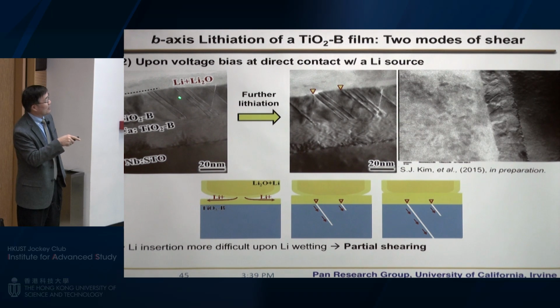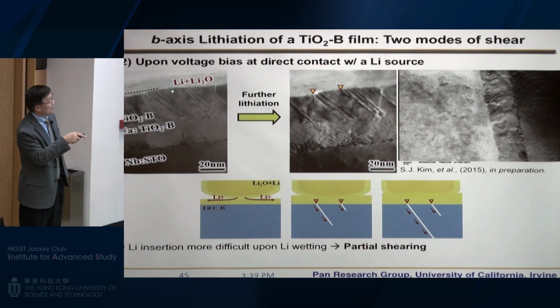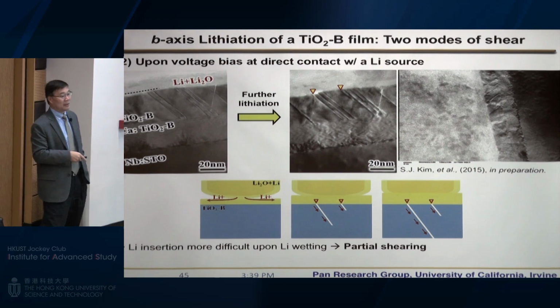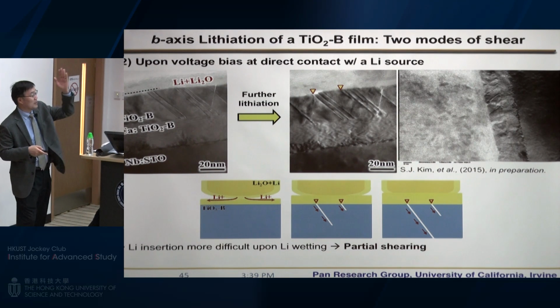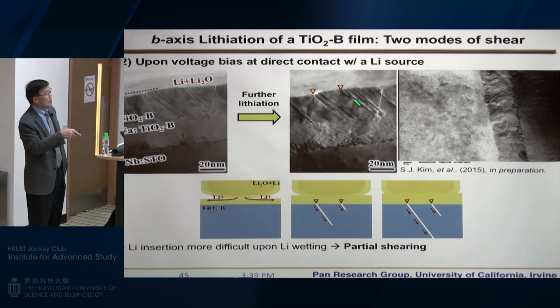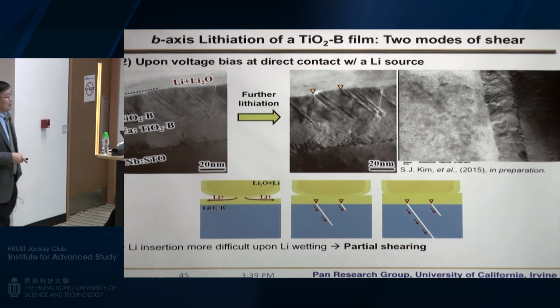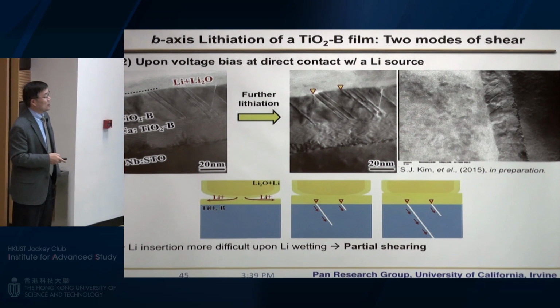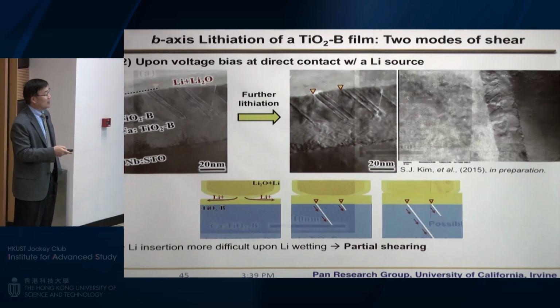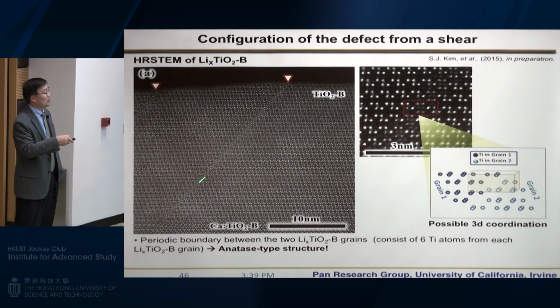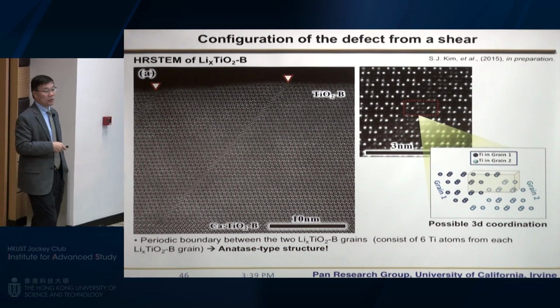And these planar defects, you can see they continue to grow, right? So you see this was not here. This was already there when we were recording images. That occurred quite quickly. Then you can see more and more of this kind of linear feature, which in 3D is actually just a planar defect. We see a lot of these planar defects nucleate. Those planar defects tend to be anatase phase inserted gradually into the bronze B structure.